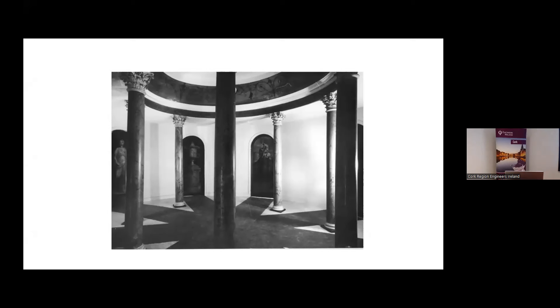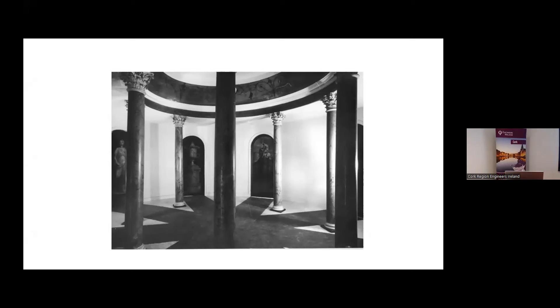Opening to the floor for questions. The first question: given the construction process and the effect water might have on the rammed earth in our climate, how did you manage the moisture challenge? We made an optimum moisture content of around 15%, but in reality 12 to 19% was fine. The soil, when you're grading and letting it air dry, naturally loses moisture. Then when the wall is built, the moisture content naturally varies on wet and dry days, and that's fine.